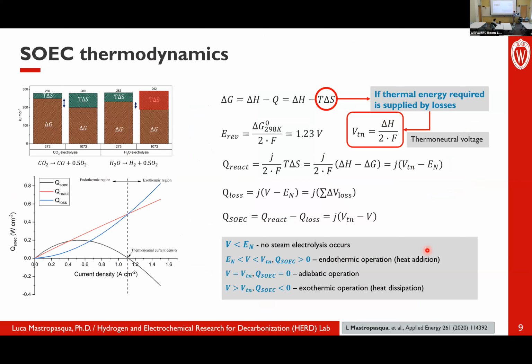From a thermodynamic perspective, the reason why heat is important is that if you look at the water splitting reaction, just look at these two bars, the delta G of your reaction decreases as you increase temperature. That means that if you perform the same process at high temperature, you would consume less electricity, which is the delta G in this figure. That happens with an increase of delta H of the whole process, because you compensate the decrease in electricity with an increase in heat consumption.